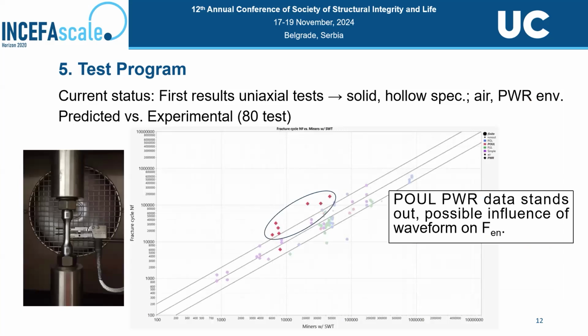Well, the current status for this test campaign is that we have finished the first phase of this campaign. We have different specimens, solid, hollow, and we have different environments like PWR. And up to now, what we have shown is that with this periodic over and underload test, we have an effect on the fatigue life. So we have this influence on the fatigue environment.